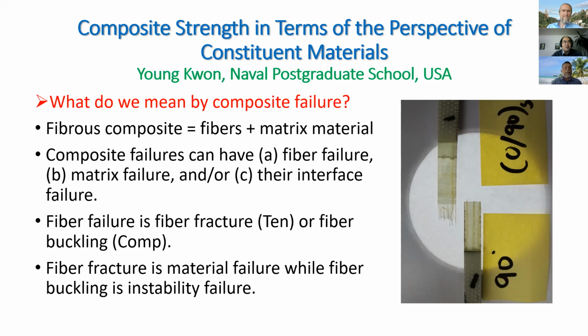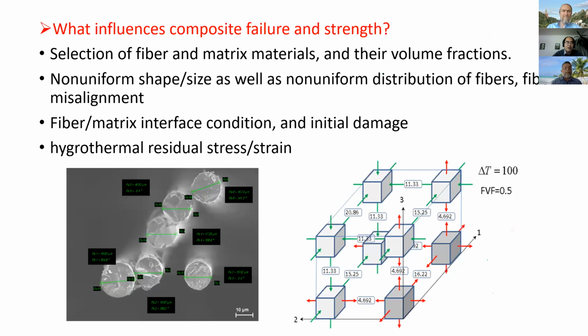However, if you look at the unidirectional composite in compression, then as you already saw with some of the fiber kinking in the previous presentation, those are not actually the material strength; those are an instability problem. So in terms of the micromechanics, fiber buckling is not a material property but rather a structural instability problem. And then going to the second question, what really influences the composite failure and eventually the strength of the composite?